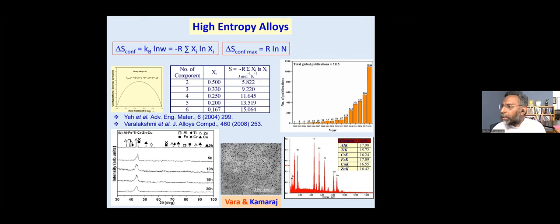If you understand a little bit of thermodynamics, thermodynamics tells us there are two types of entropies. One is thermal entropy, caused by heating of a material, the randomness that is created because of thermal vibrations. The second is when you add other solute atoms into a material, and if these solute atoms are randomly distributed inside the material, then you get an additional entropy called configurational entropy. This configurational entropy keeps on increasing as we go to the center of the phase diagram.